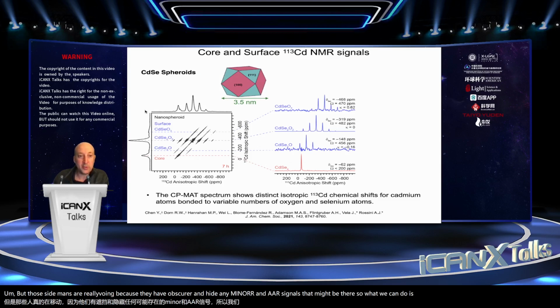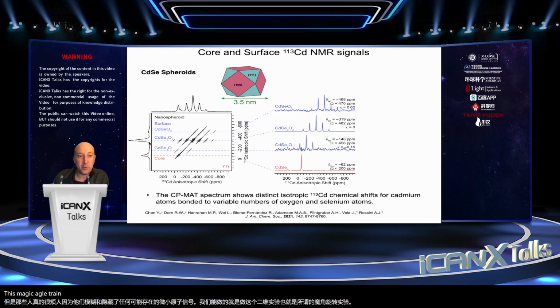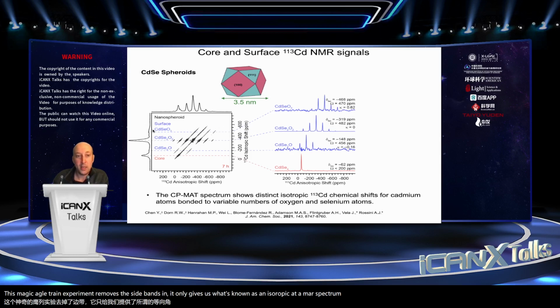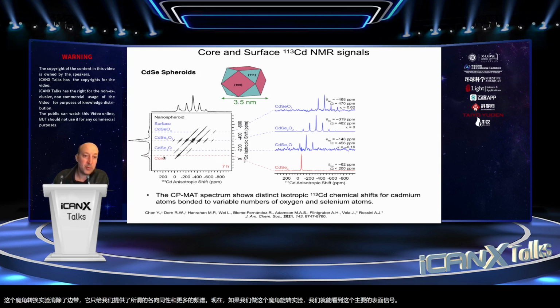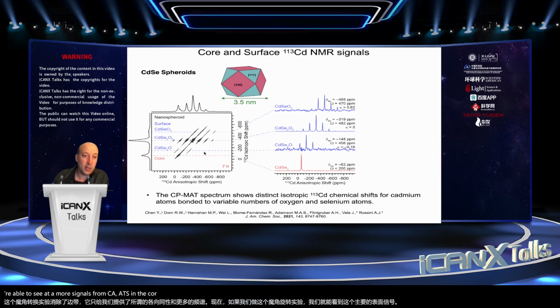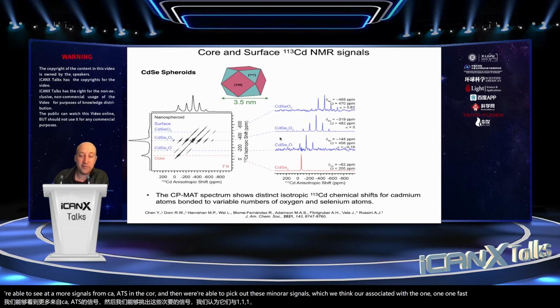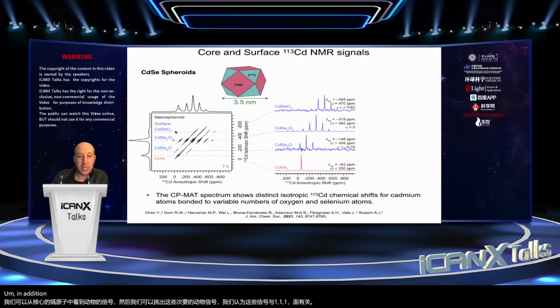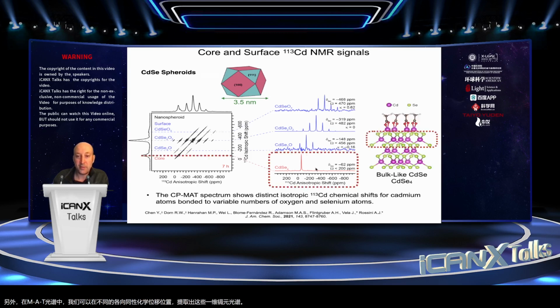So what we can do is go to this 2D experiment that's known as a magic angle turning experiment. This magic angle turning experiment removes the sidebands, and it only gives us what's known as an isotropic NMR spectrum. So now if we do the magic angle turning experiment, we're able to see this major surface signal. We're able to see NMR signals from cadmium atoms in the core. And then we're able to pick out these minor NMR signals, which we think are associated with the 111 facets. In addition, in the MAT spectrum, now we can pull out these 1D cadmium NMR spectra at different isotropic chemical shift positions. And if we look at these spectra, they provide us with useful structural information.